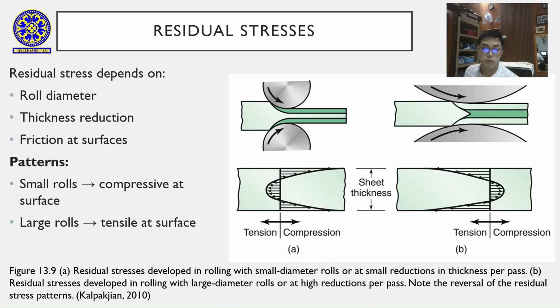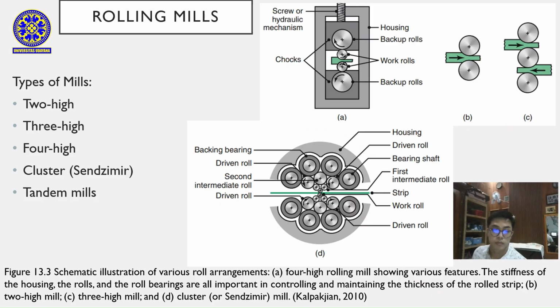Residual stresses form due to non-uniform deformation during rolling. Small diameter rolls or small reductions tend to deform the surface layer more than the center, creating compressive stresses on the surface. Large diameter rolls or large reductions deform the bulk more, producing tensile stress at the surface. Residual stress can affect dimensional stability and must be considered in subsequent forming or machining processes.